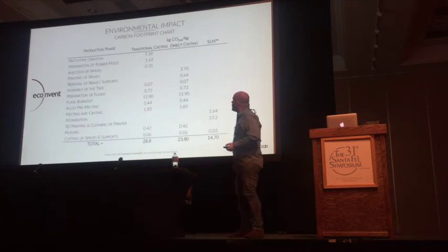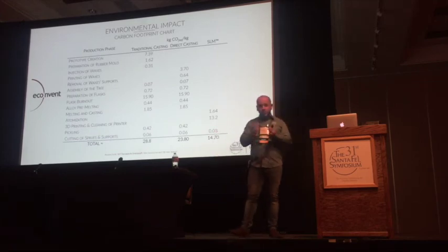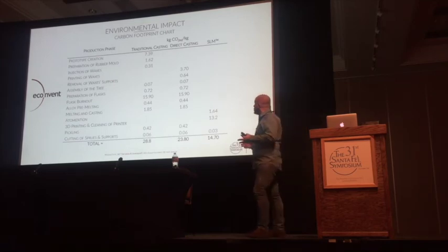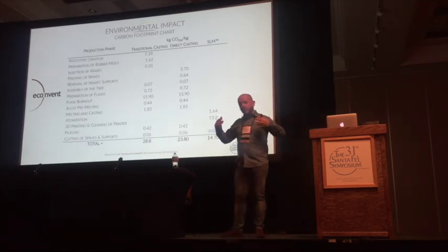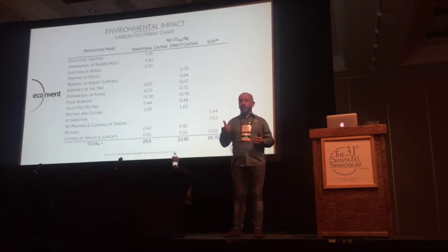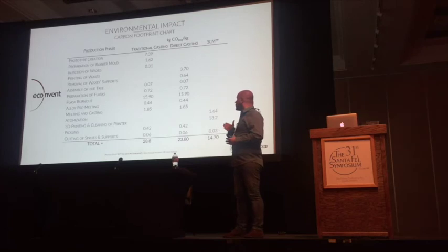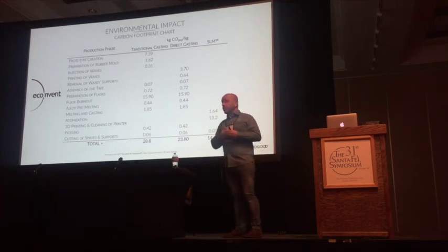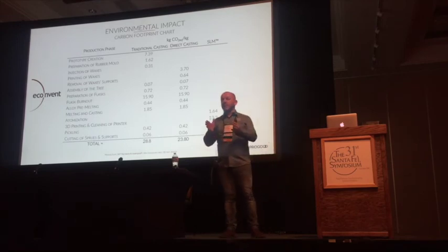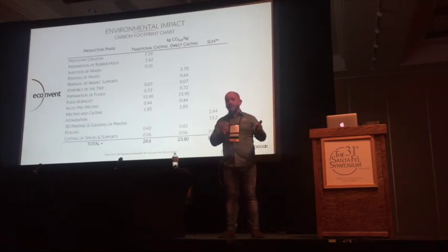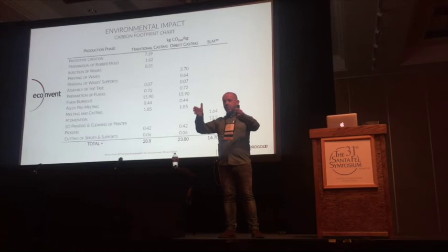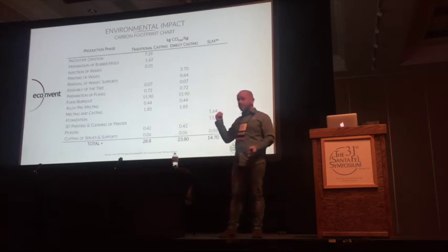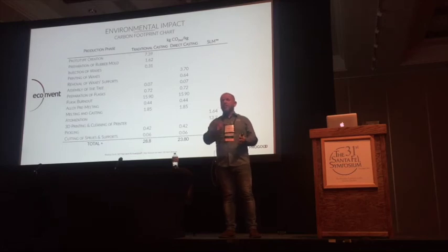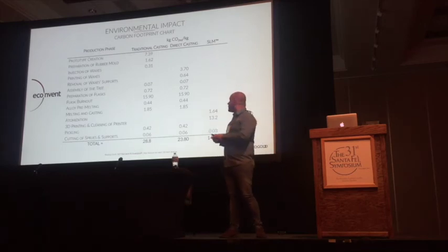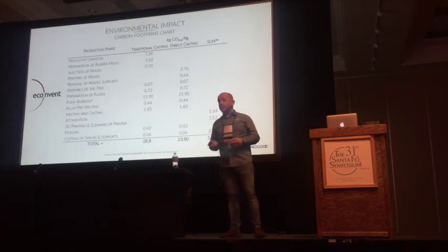Then we were doing a carbon footprint investigation. So we wanted to see how much CO2 is producing every single process to produce 1 kilo of jewelry. And this, according to the process yield, because it's very common that in casting, factory that has 10, 20 people, they do not fulfill the burn-out furnace every day. Maybe they have burn-out furnace of 16 flasks, like the one that we were taking into consideration, and they just put 3 flasks. But the carbon footprint is the same, so 15 kilo of CO2 produced.